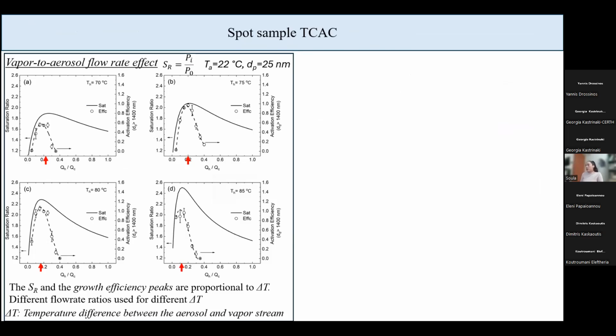First, I wanted to see what is the optimum vapor to aerosol flow rate that I have to use. Each subplot here is for a different temperature of the water that was being used. The water was being heated up to 70, 75, 80, 85 degrees Celsius. The solid line represents the calculated saturation ratio, which in all cases was above 1, and that showed that we can expect activation and further growth of the droplets.